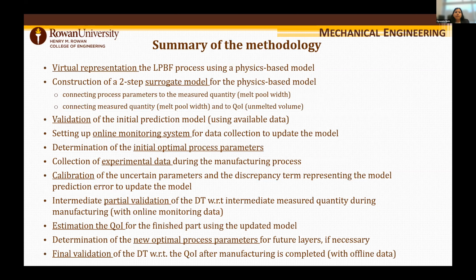So this is the summary. We start with a virtual representation, do the two-step surrogate, and validate the initial prediction model. We collect data from the online process monitoring system, find the optimal process parameters, collect experimental data, calibrate the model parameters, and that is how we update the model, do the partial validation, and estimate the quantity of interest. If it is okay, then we continue. If it is too bad, we terminate the process. And if it is somewhere in between, then we set new process parameters and continue the process like that.